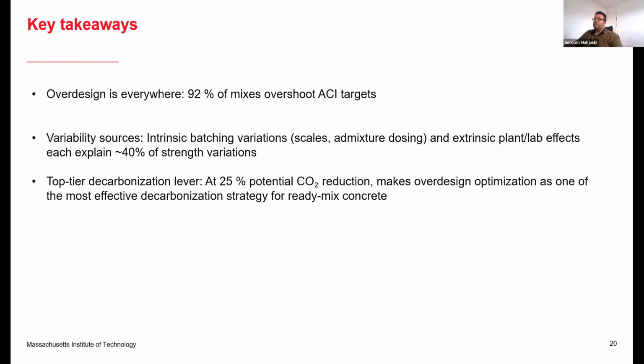Here are the takeaways from this study. Overdesign is significant. Excess overdesign is significant in industrial mixes, and 92% of the mixes overshoot ACI targets. And the variability sources were studied here, and intrinsic batching variations and plant and lab variations each explain 40% of strength variations on average. This is one of the top tier decarbonization levers, and we can potentially reduce the GHG emissions by 25% by overdesign optimization.